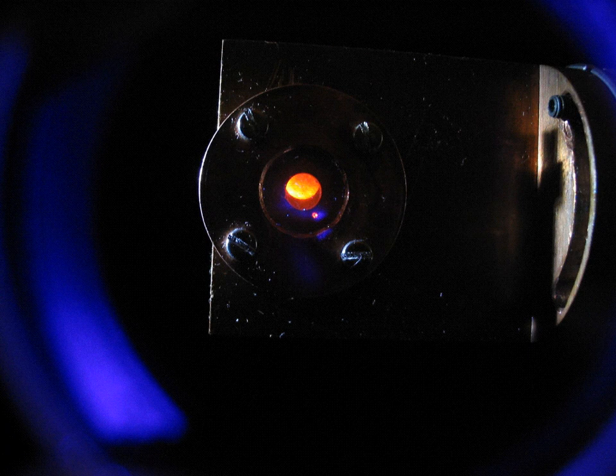Most synthesis routines yield a mixture of different actinide isotopes as oxides, from which a certain isotope of curium needs to be separated. An example procedure could be to dissolve spent reactor fuel in nitric acid, and remove the bulk of the uranium and plutonium using a PUREX-type extraction with tributyl phosphate in a hydrocarbon. The lanthanides and the remaining actinides are then separated from the aqueous residue by a diamide-based extraction to give, after stripping, a mixture of trivalent actinides and lanthanides. A curium compound is then selectively extracted using multi-step chromatographic and centrifugation techniques with an appropriate reagent.